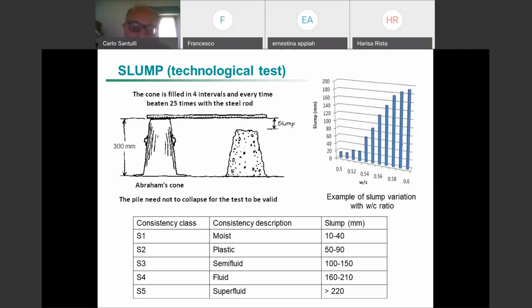What we want to see here is whether our concrete would collapse, because one occurrence in concrete is that the wall collapses before ending the cure period, even in some cases later on, but in most cases during cure, because it's drying, and water is coming out, reducing the water vapor depending on the temperature. Anyway, you have this kind of percolation, and the wall collapses under its own weight.